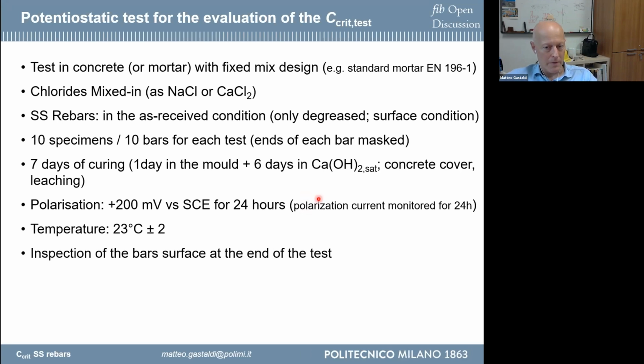Then for the test, first of all you have to decide what concrete we want to use. Concrete or mortar, the mix design is fundamental to fix. You can consider using a standard mortar, for example. You mix in chloride, and here there is a problem related to the type of chloride that you want to use, sodium chloride or calcium chloride, because we have different effects. With sodium chloride, generally you have a higher chloride threshold. With calcium chloride, you have a lower chloride threshold. Stainless steel rebars have to be used in the condition related to the production and only degreased. In this way, you can evaluate the real chloride threshold, considering the real surface condition of the rebar.